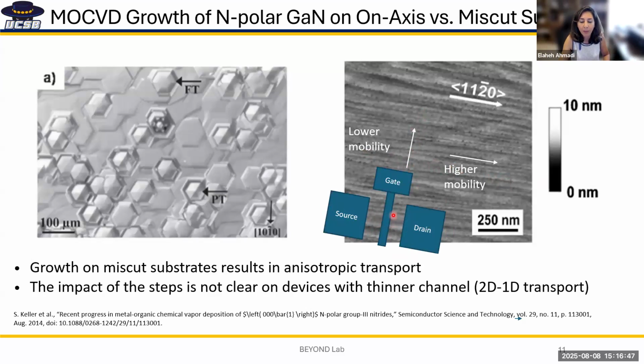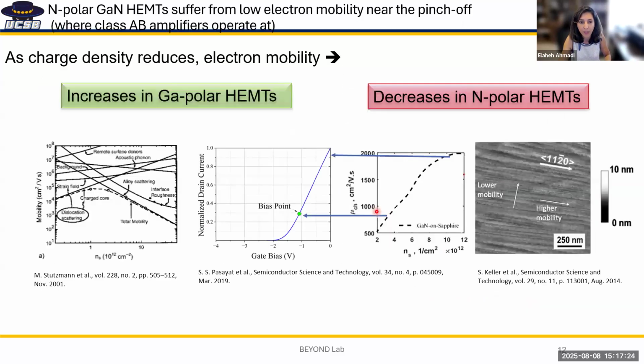When I started as an independent PI, my focus on axis was that as we are trying to scale these devices and go to narrow, thinner channels, then the step height can become comparable with the channel thickness, and we don't know at that point if we can see new challenges because of confinement and having 2D, 1D transport. And so that was one reason that we focused on axis substrates.